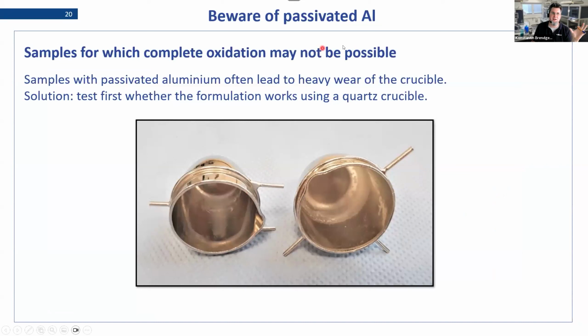This is very effective for aluminum particles, because what we found, and what a lot of people have seen in the recent past, is that a lot of recycling materials, secondary resources basically, come with passivated aluminum inside. So the problem is you have a particle that has a metallic core of aluminum and then an outside shell of aluminum oxide. So from the outside, you can't get to the metallic core. Well, at least not thermally by just putting it in a furnace.